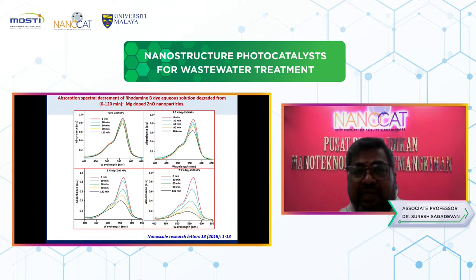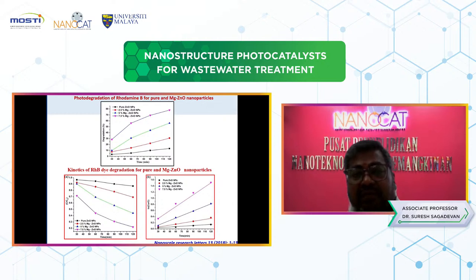You can look here at the same UV absorption spectrum for the Mg doped zinc oxide nanoparticle with various doping percentages of 2.5%, 5%, and 7.5%. The first figure represents pure zinc oxide nanoparticle. You can clearly see how the absorption decreases with increasing time, but the one that shows the most variation in this UV spectrum is especially the 7.5% Mg zinc oxide nanoparticle, because it shows that it is highly degraded compared to the other percentages. You can look here at these figures, as we calculated for the kinetic studies the degradation rate constant, R-squared value, as well as degradation percentages, which are tabulated.